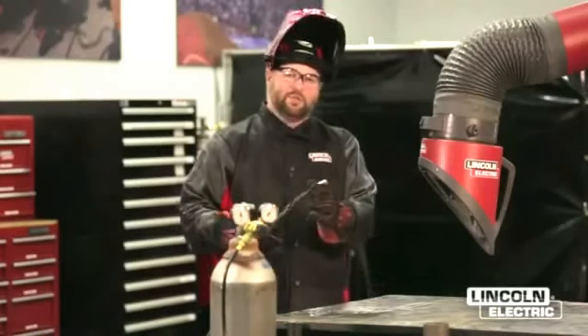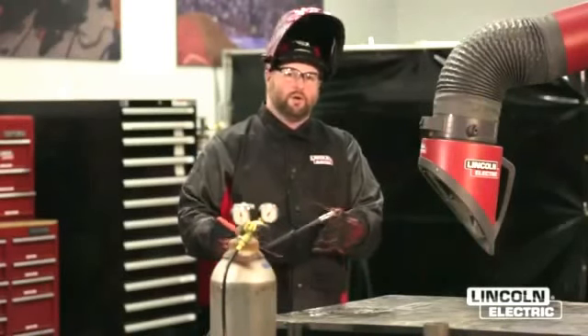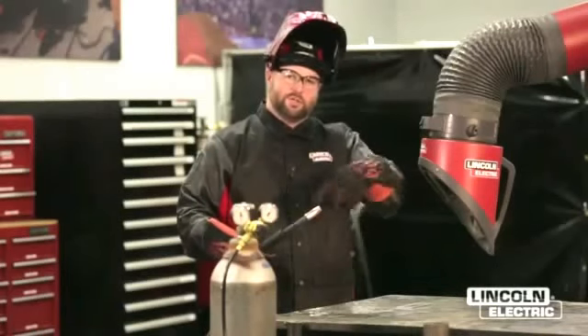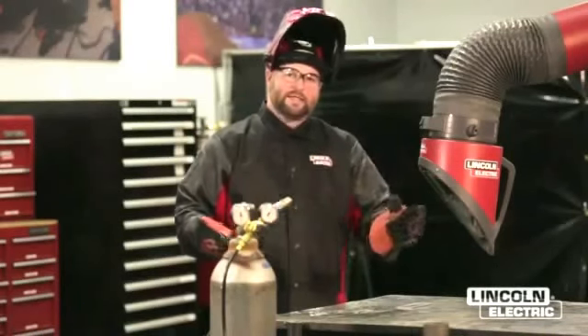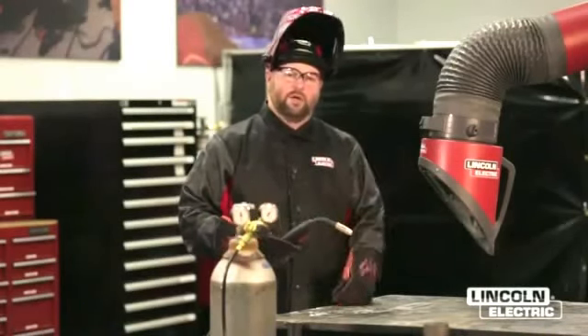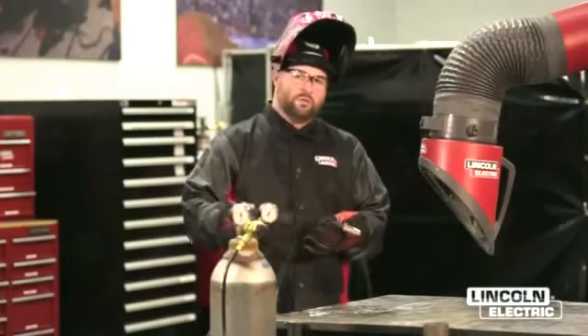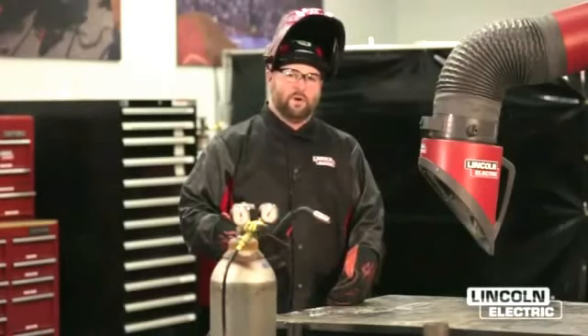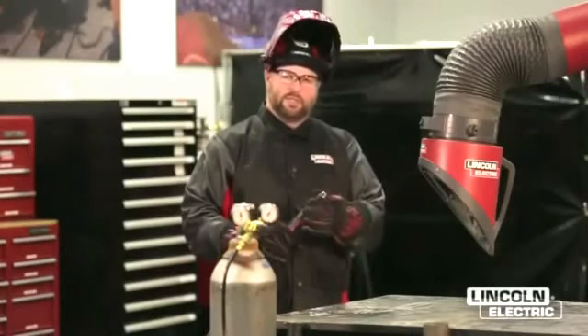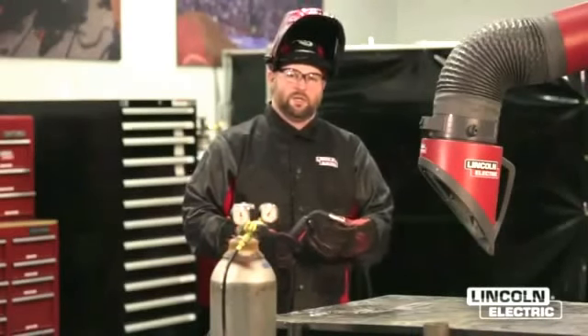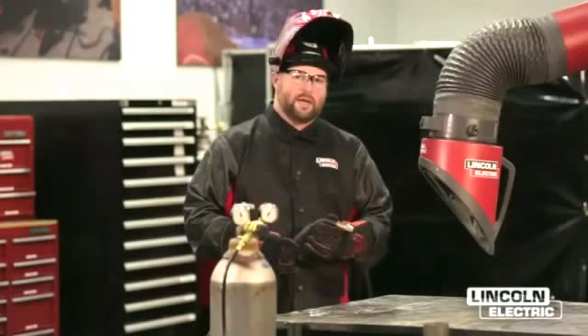What happens is as you turn the flow rate up too high, number one, you're wasting gas. Number two is you'll start to get a swirling effect, and that's actually going to bring in the air and also contaminate your weld. So use the recommended factory settings on your gas flow rate. For this particular setup with this small nozzle, 15 cubic feet an hour is typically fine.